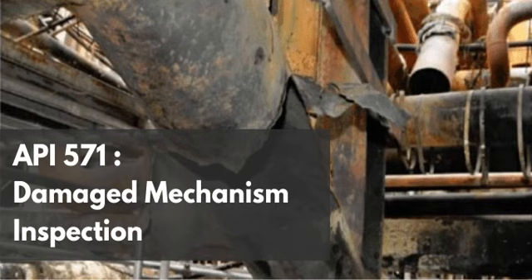Oh, so it's almost too late. Usually, yes. The source explains the visual and dimensional field cues of severe damage: bulges, heavy scale, thin lip, brittle cracking, and what it specifically calls thick lip tube failures. It also mentions that the cracking can manifest in a distinct crow's feet appearance.